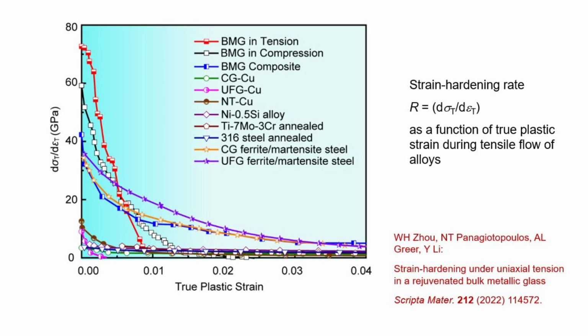The red line is for the bulk metallic glass in tension. Hardens enormously fast compared to conventional materials. And the wise people in the audience will realize this is, of course, actually bad news, not good news. Because if you're hardening that fast, you can't keep it up for long. And the real good news would be to spread the hardening out over a longer time.